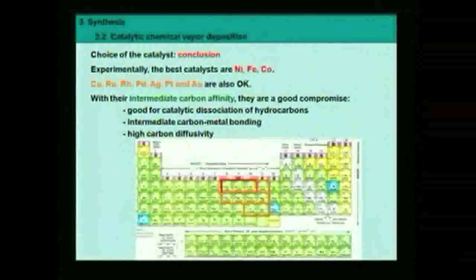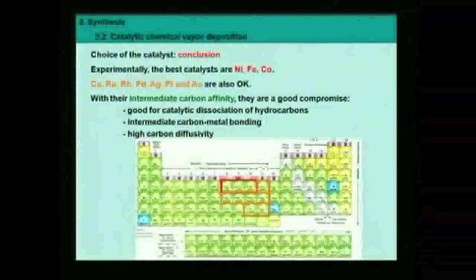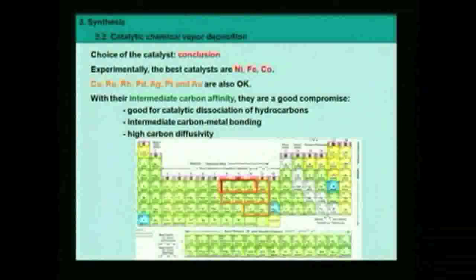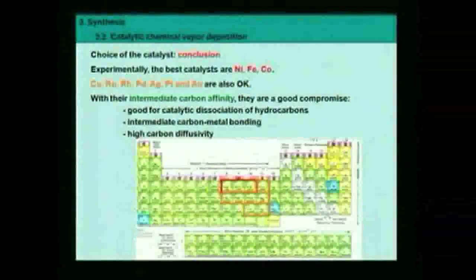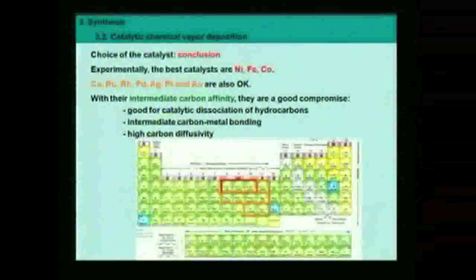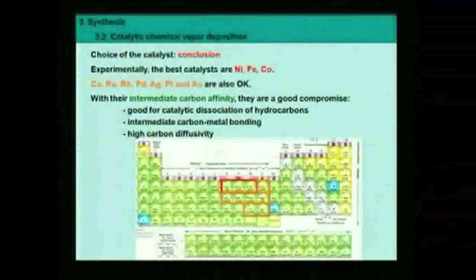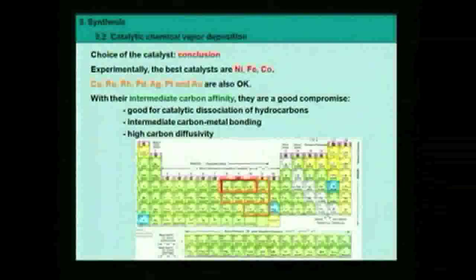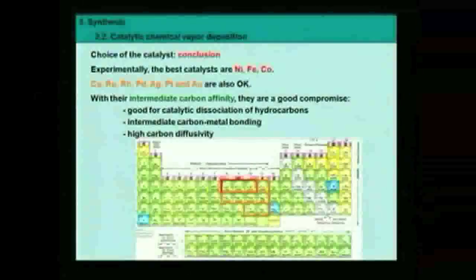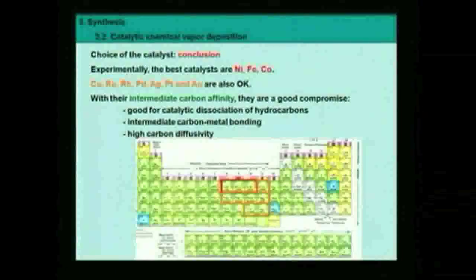At the end of the day, experimentally, the best catalysts are found here in the middle of the periodic table. Iron, cobalt, nickel are the best elements to catalyze the growth of carbon nanotubes and graphene. Other elements around those, like copper, silver, gold, palladium, platinum, rhodium, and ruthenium, are also okay. They work, but usually you need to optimize the growth conditions for them to be sufficiently active. With nickel, iron, and cobalt, they will be most of the time quite good in any condition. Okay, this is for the choice of the catalyst and the rationale for that.